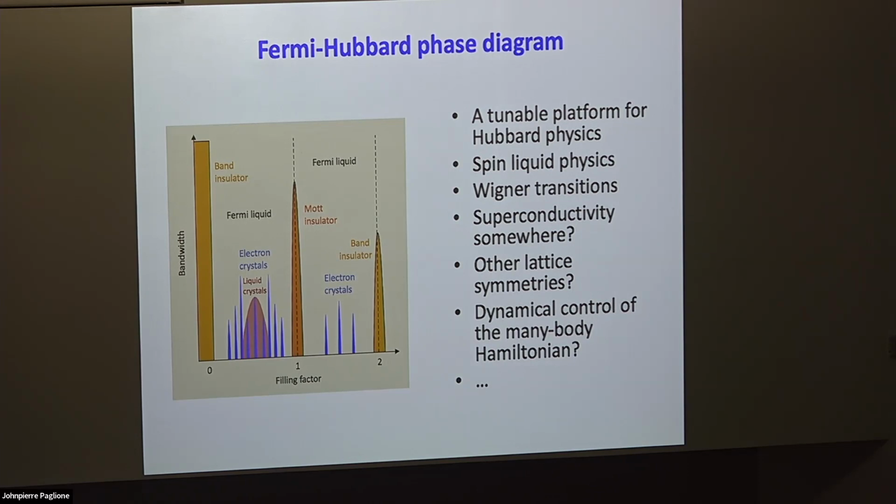There are different ways of measuring compressibility. You can measure capacitance, or, as mentioned yesterday, you can do optics to look at the dielectric response. So at this point there are already many different ways that people study these electron crystals, also including STM, which can directly image them as well. Yeah. Any final question?